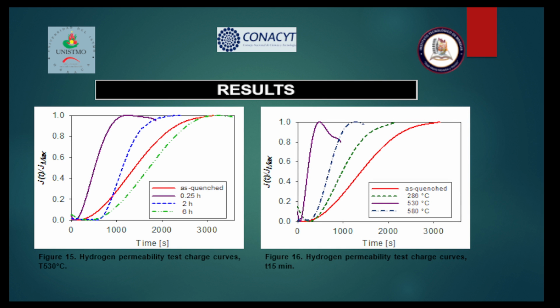Hydrogen has different permeation rates due to the different traps present in the microstructure, grain boundaries, or precipitates of alloy carbide. In the first figure, figure 15, it is observed that the longer the tempering time, the more time is needed to reach the steady state. On the other hand, in the following figure, figure 16, it is observed that at a temperature of 530 degrees, there is a rapid saturation of hydrogen in the sample.